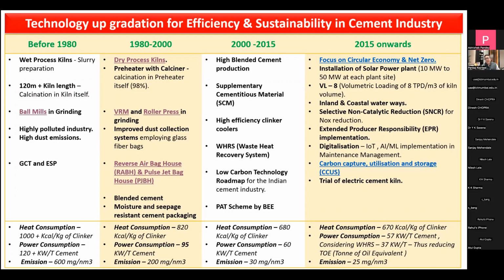But the main thing which has helped in this is that earlier we were using only ordinary Portland cement. Now the world has moved towards blended cement. In blended cement, we are using supplementary cementitious material like fly ash or slag, which is helping us to reduce the clinker factor, and at the same time it is reducing the power consumption, the heat consumption, and everything, leading to more and more efficiency in the process.